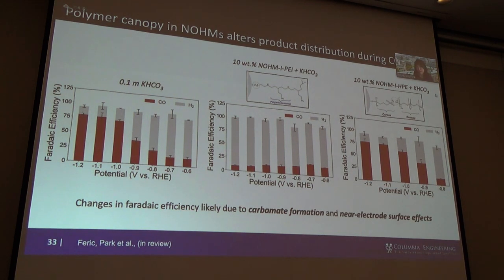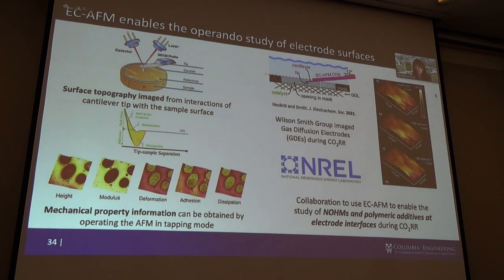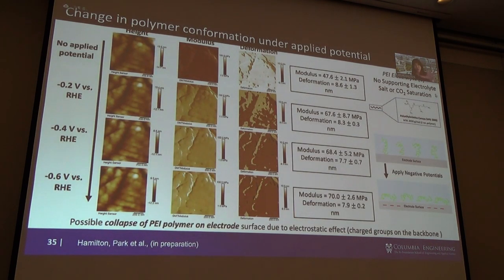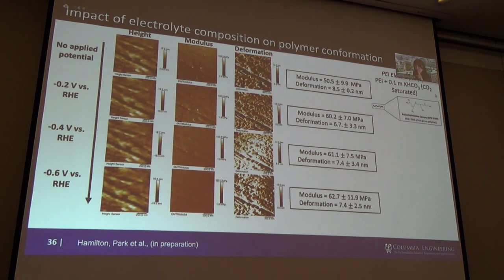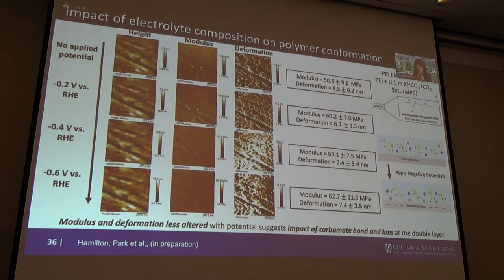So we were really curious what happens at the electrolyte-electrode interface. So we went to NREL and tried to understand what happens when polymers get adsorbed and deliver CO2 to the surface of the electrolyte and electrode interfaces. Without going into too much detail, this is basically showing the modulus and deformation during the actual electrochemical reaction. When you have a very short brush and apply the negative potential without any CO2, the polymer collapses onto the electrode. But if you have a case with CO2 in the system, there is a very different conformation, allowing much better transport between these polymer chains onto the surface of the electrode. And that's how all this transport and electrochemical reaction was changing.